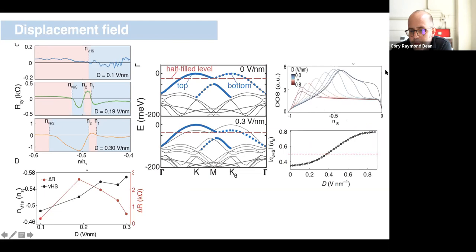Okay, so we can be slightly more precise than that. Here we're plotting the density of states as a function of filling of the band, and each color corresponds to a different displacement field value. And what we see is that indeed, the peak density of states, which coincides with the single particle Van Hove singularity, shifts rather dramatically through the band as we vary the displacement field that we apply.